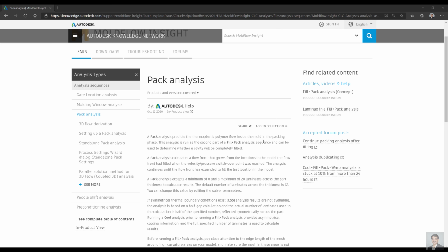In this episode, I am going to discuss optimizing the packing profile. Packing profile or packing analysis comprises the addition of extra polymer material to the cavity so that we compensate for the shrinkage. During the tooling, we expand our cavity to compensate for that shrinkage, but at the same time on the machine we put in excess material to compensate for or minimize the shrinkage.